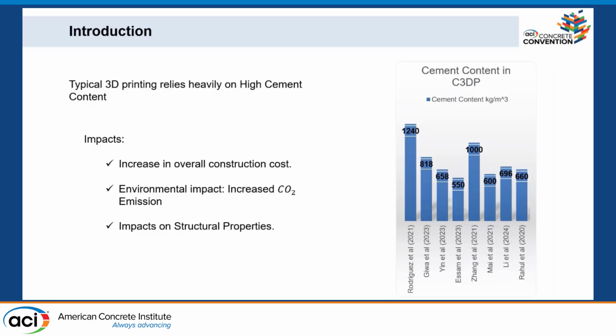But the problems don't stop there. You might think that using more cement means a stronger structure, but that's not always the case. It actually increases the chances of shrinkage during the curing process. This leads to cracking, weakening the overall structure. Additionally, high cement mixes can be more vulnerable to attacks from chemicals in the environment, reducing the long-term lifespan of the 3D printed cement. So you can see simply throwing more cement at the problem isn't the solution.